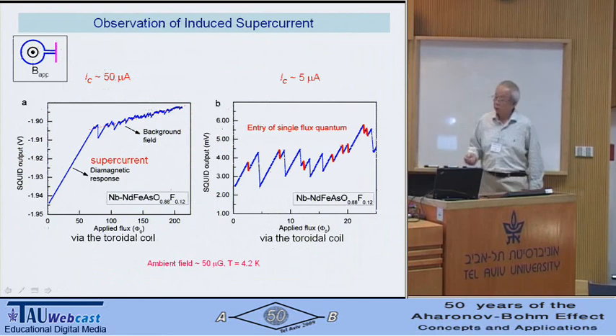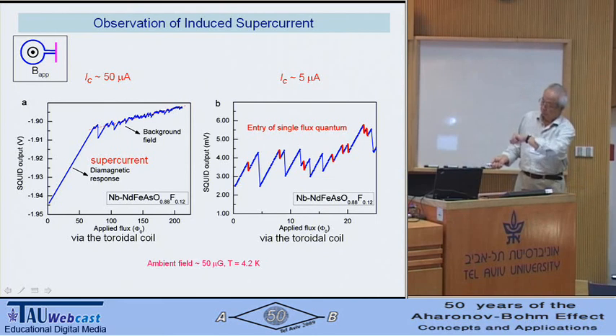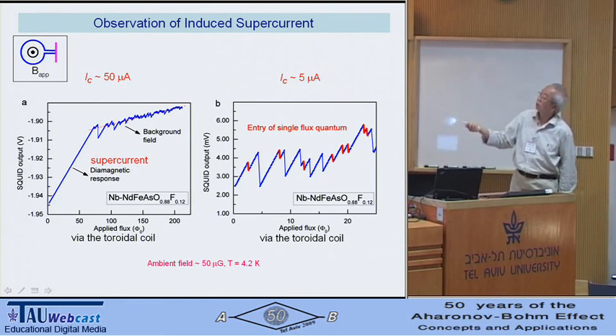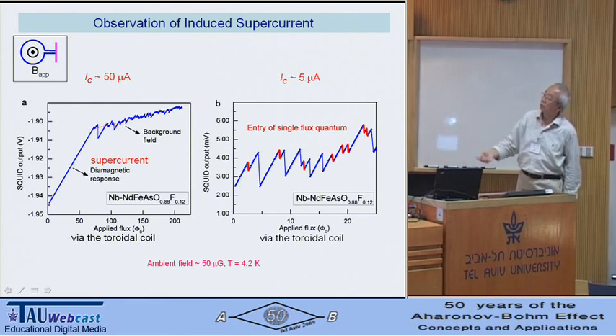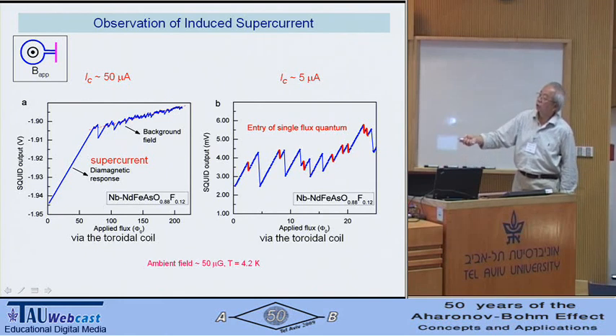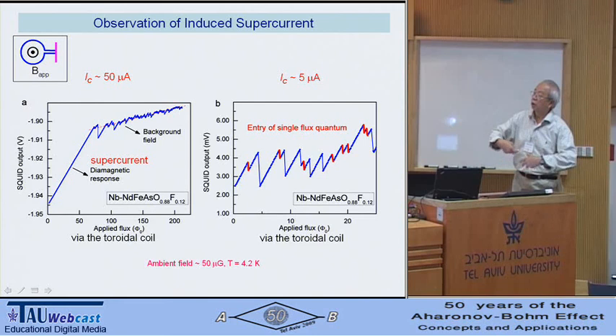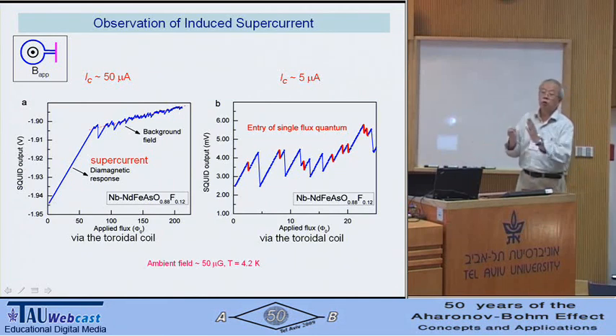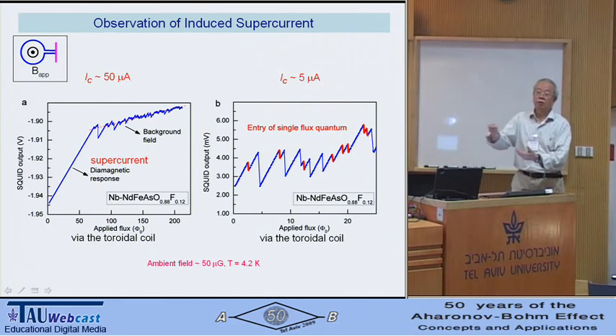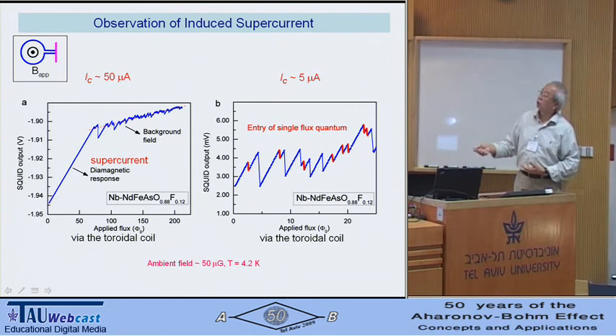Here's the results. As you increase the field, here's the loop with the magnetic field in it. As you apply the flux, the system develops a diamagnetic response. So you get a supercurrent going up and up with the magnetic field until it reaches a sort of critical value, critical current. And then what happens is that it will let flux come in or out. That's why you see the zigzag. That indicates that the flux starts coming in and out of the ring.